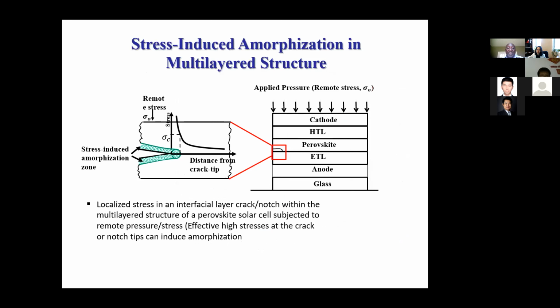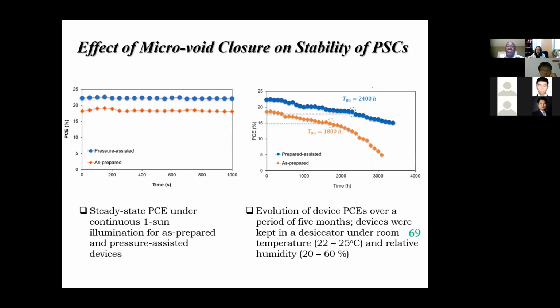Now, what also happens is that as you apply the pressures, you also have some stress-induced amorphization around the interfaces. And that stress-induced amorphization is part of the story of what is going on as we apply pressure. And more recently, we've been able to show that as we apply pressure and we close up the pores and voids, you increase the stable lifetimes of the solar cells in ways that suggest that further understanding of the transport phenomena associated with these structures could enable us to develop more stable perovskite solar cells in the future.